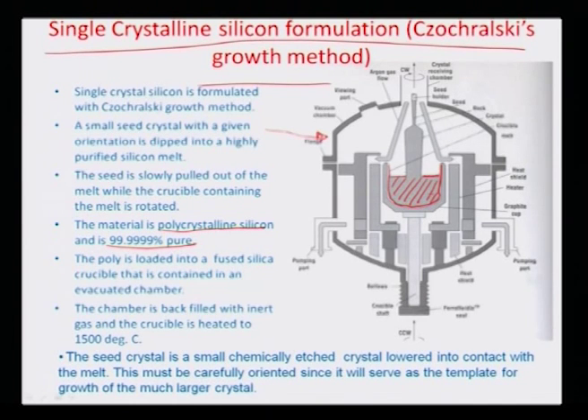And this crucible is basically capable of rotation. So you can rotate the whole crucible, and also it is inertly filled, so the chamber here is evacuated using pumping mechanisms as illustrated here and here, and then you can fill the whole atmosphere of this fused silica container with argon or an inert gas, so that it ensures the non-inclusion of material like oxygen or nitrogen into the silicon lattice. So it's an extremely pure process, and there are certain foundries in the world, like one example is MEMC, which is based in St. Louis, Missouri, which manufactures high purity single crystalline silicon wafers.